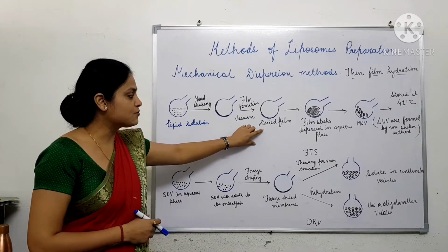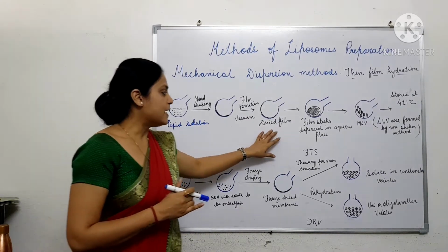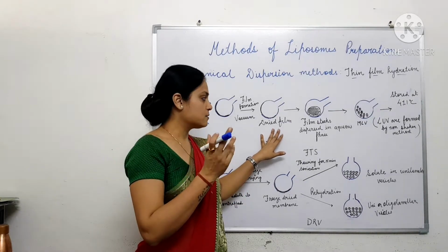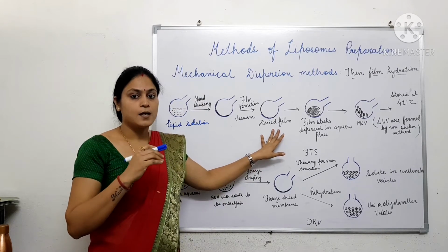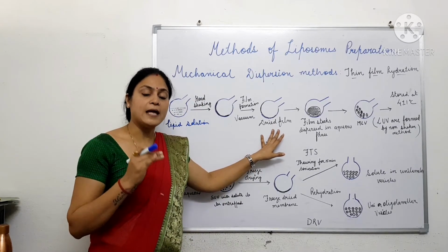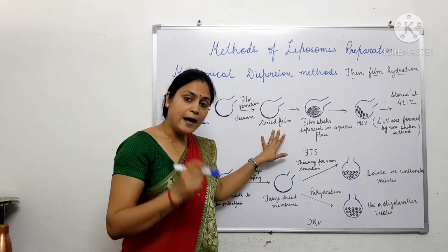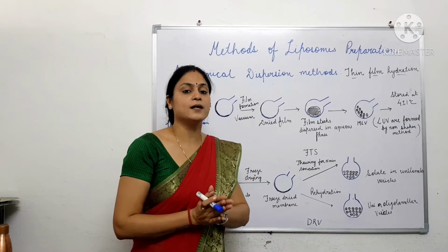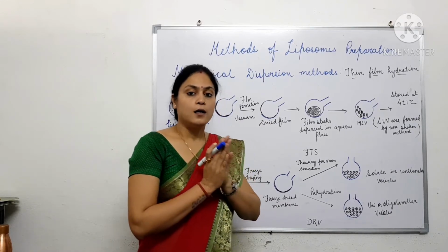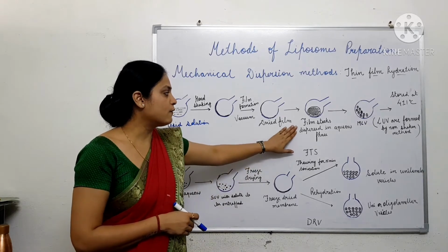This lipid film is dried in a nitrogen environment, and then the dried lipid film is hydrated with the help of an aqueous solution, maybe a buffer. If a hydrophilic drug is to be incorporated, then this hydrophilic drug should be added in the aqueous phase which is used for the hydration of the film.